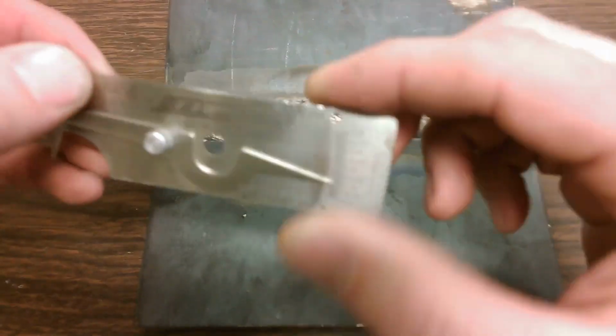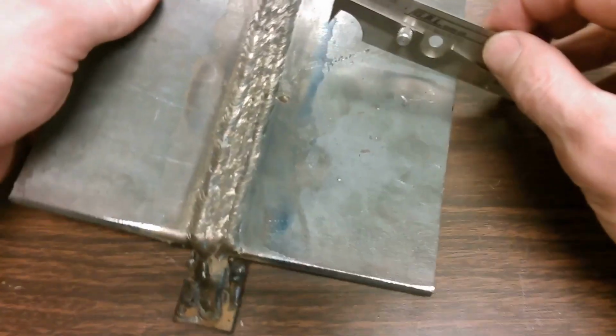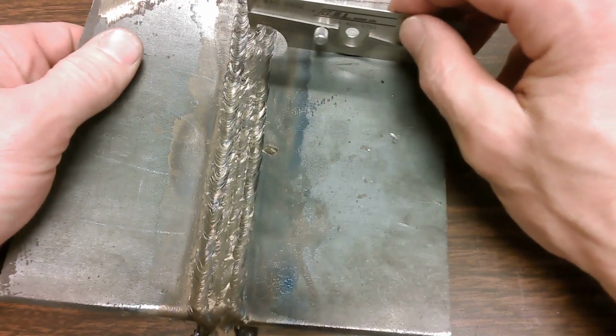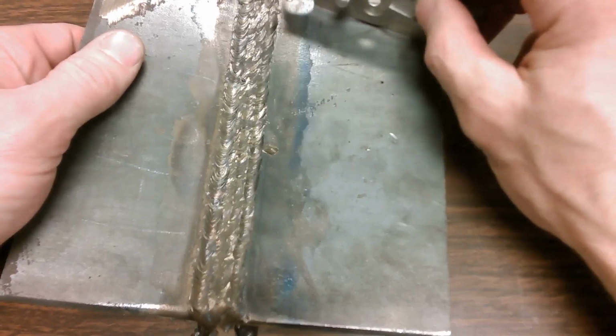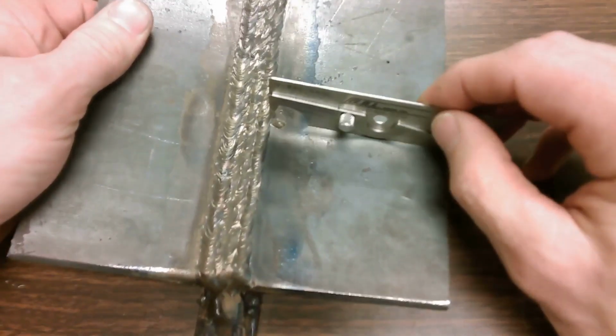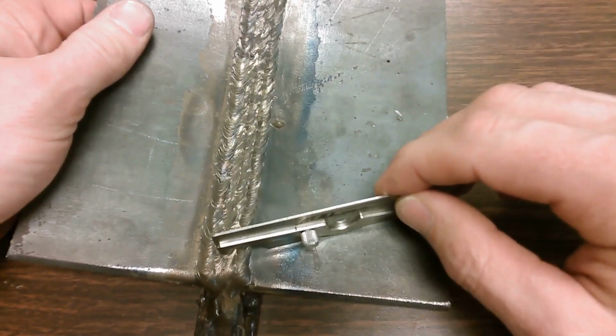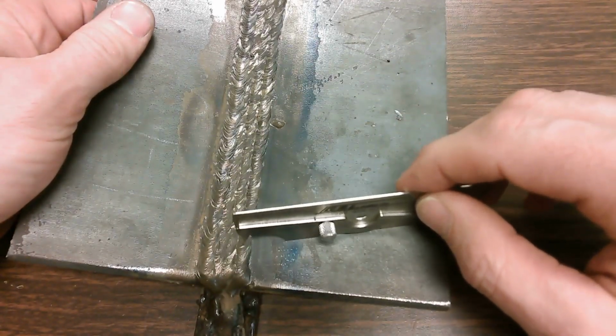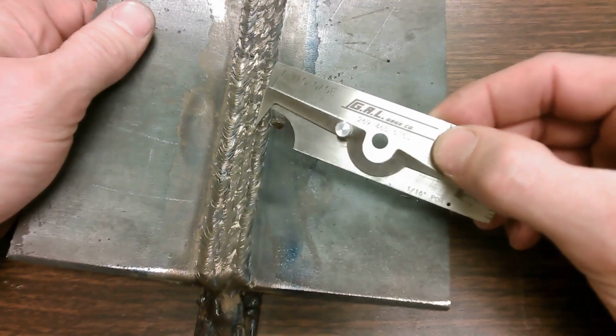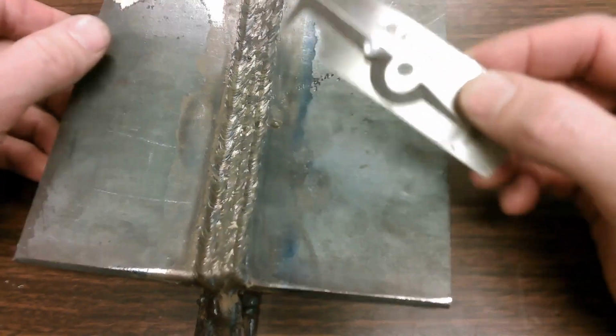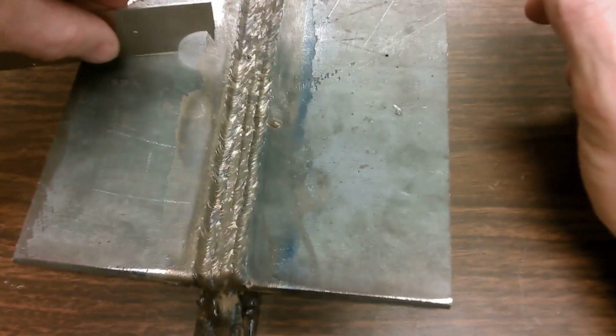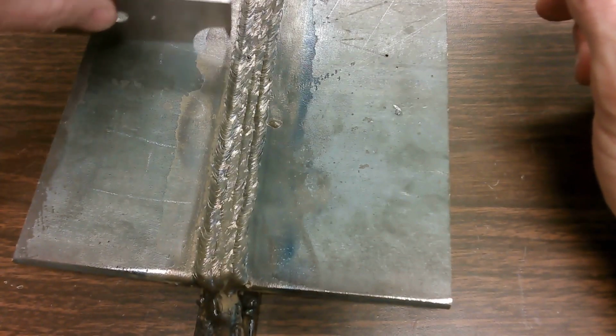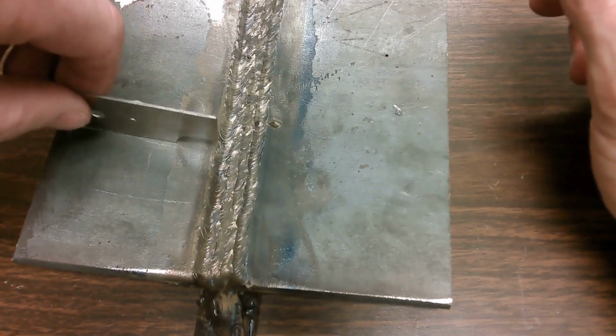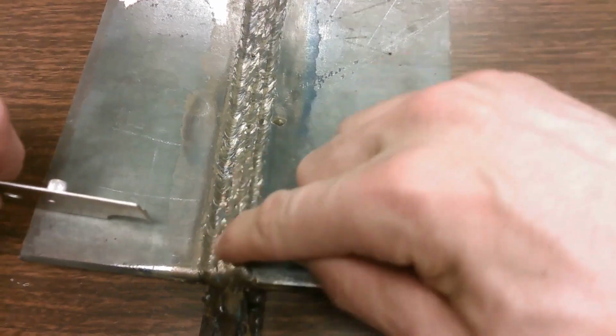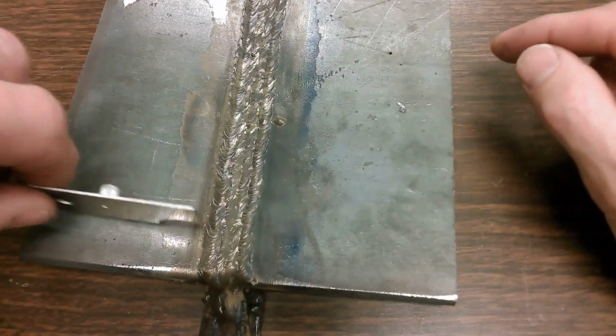And I'm going to lock that in, make sure it doesn't move, and then all I do is just slide over the top and make sure that I'm clearing everything. Any high spots, I'd want to identify those first and make sure that that 1/8 inch is completely clearing. I check in both directions, and the plate does get warped a little bit during that process. So, identifying where the highest points are and then checking those.